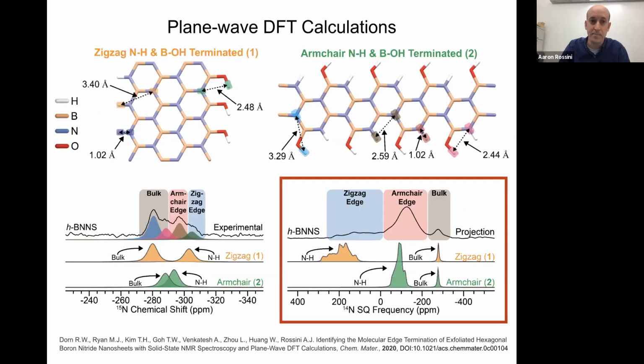So that really does confirm that we have those amine groups on the edges of the sheets. We can also calculate the nitrogen 14 NMR spectra. Now the nitrogen 14 NMR spectra, the peak positions and shapes are going to be determined by both the chemical shift and the nitrogen 14 quadrupole parameters. And we can simulate both of those effects based upon the calculated values. And you can see that in some ways, the nitrogen 14 more nicely resolves the different edges, the armchair edge and the zigzag edge.